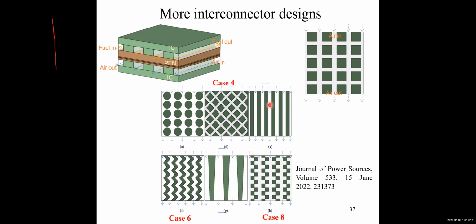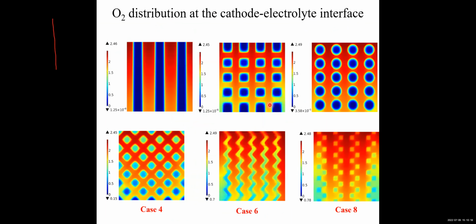We also designed different interconnector configurations and did the simulation. I want to show you some selected results. These figures show the oxygen concentration at the cathode electrolyte interface. This is the conventional design, and you can see the oxygen concentration under the channel is pretty high, but under the rib is very low, which causes a low average cell power density.